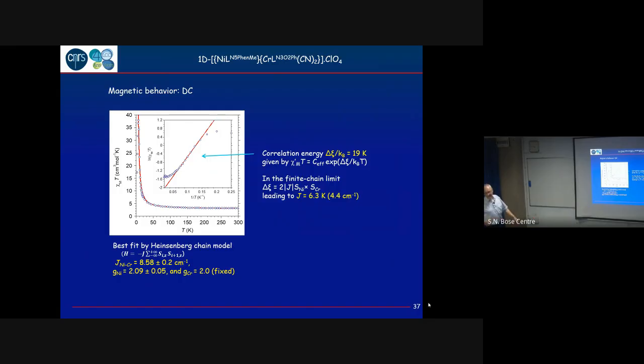Okay. So can you please explain from the chi-T versus T behavior, how do you get the ferromagnetic behavior? What is the fitting then? Oh, chi-T versus T? Yes, here there is a model that has been developed for chains, and you can very easily fit. So we fit only, let's say, in the high temperature domain, because the model does not take into account the anisotropy, and so you cannot fit everything. So I don't remember, but I think here we stop around 10 or 15.